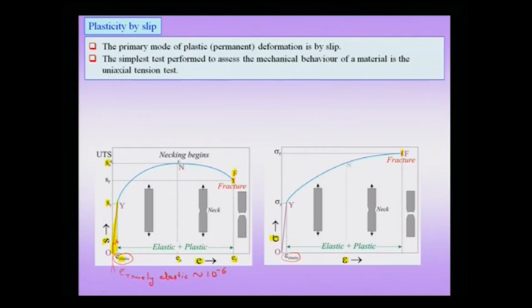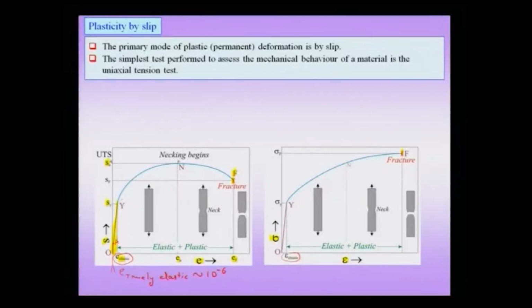This strain is extremely small, and therefore, beyond that region, the curve appears straight from A to Y. So, from point A to Y, the curve is straight. So, this is macroscopically elastic, but at microscopic scale there is actually some plasticity which is already taking place. The reason behind this plasticity, we will see soon, is motion of dislocations leaving the crystal or the grain boundary.